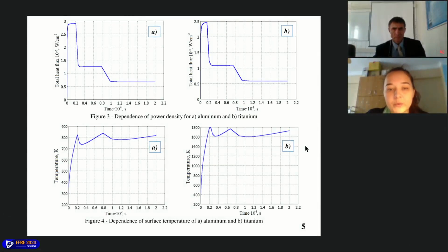In the framework of my experiment, a solution of the heat equation for aluminum and titanium was also shown. On figure 3, you may see the dependence of power density for both materials, and they have a similar function. Using those functions, we get a solution of the heat equation, which is presented in figure 4.